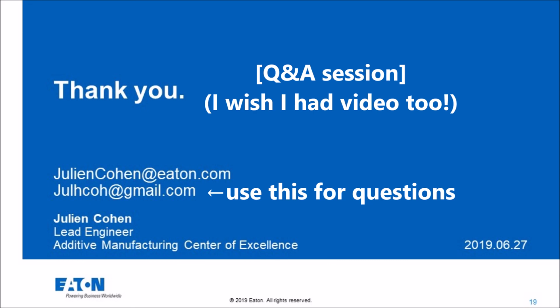Our aerospace division makes parts and assemblies of these parts that we sell to the aerospace primes like Airbus and Boeing. So Eaton's goal broadly is how do we inject as much additive manufacturing as possible where it makes sense into our aerospace portfolio. There are tons of casting replacements, for example, that can be done well with additive. And from my perspective within Eaton, we'd like to generalize as much as possible. So we do create these qualified metallurgical processes. For example, right now with aluminum, silicon, ten, magnesium is the main material we're working with, among some others. We do have standards about what we expect to get out of the material in terms of bulk properties, like ultimate tensile strength, elongation at break, those general mechanical properties. So generalize as much as possible, and then where necessary, get application specific, whether that means internal geometries or thin walls or whatever is required for that application.